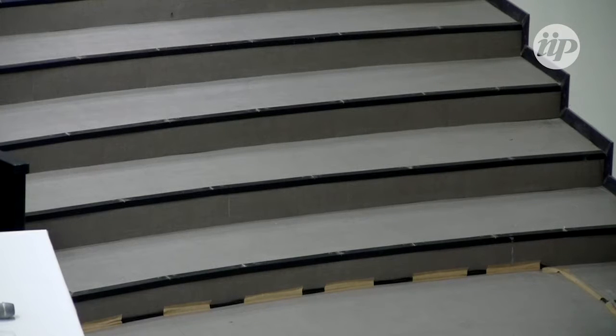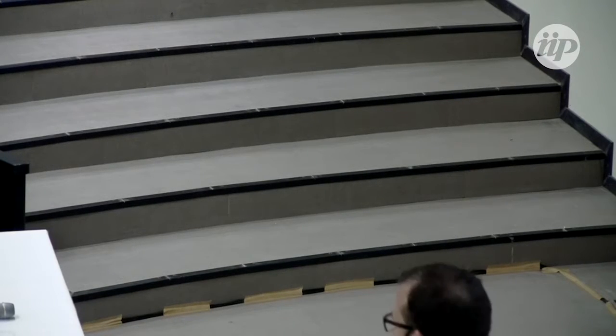Again, we looked at the phonon dispersion of the material. We see no negative frequency, so we know we can go ahead. We calculate the thermal conductivity. And what we find now is that this material does not have an isotropic thermal conductivity, which means it makes a difference if you conduct heat in one direction or in another direction. The difference is not very large, but it is there.